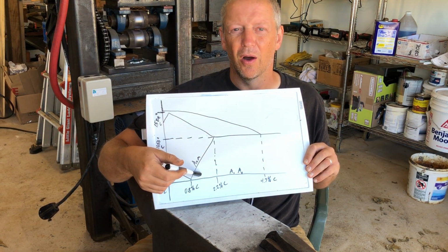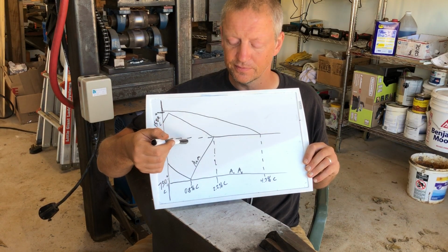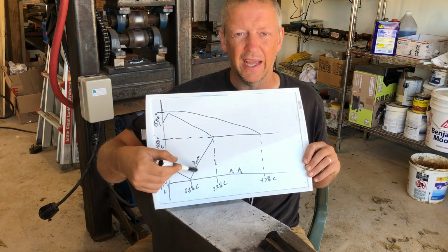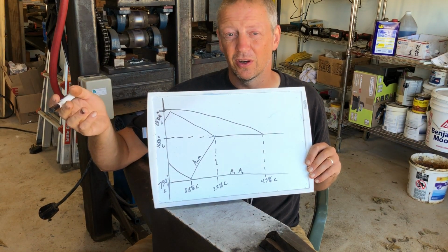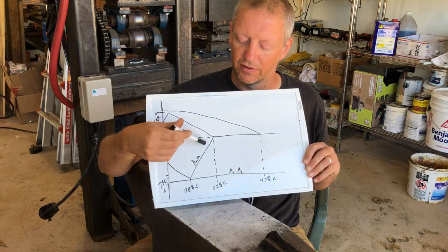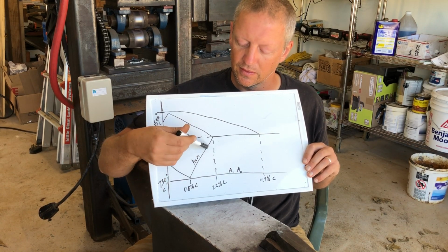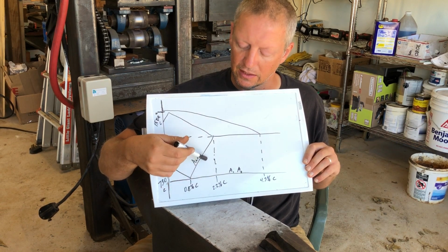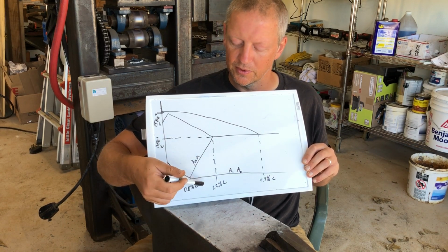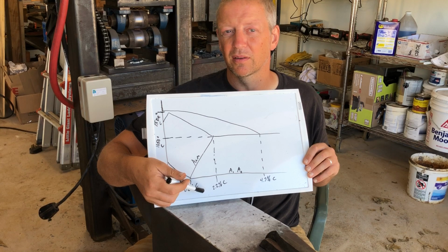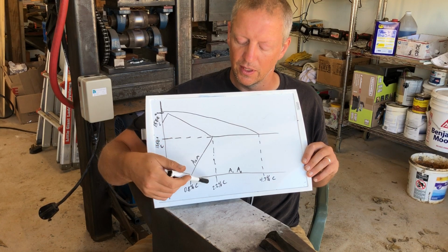Depending on how large your carbides are, depending on how fast you are heating, it's going to actually affect the location of this line. As I noted earlier, adding alloys affects the location of this line. So we're really going to be talking about the ACM line and this zone over here, which is really where we're talking about with Wootz, from about 1.3% carbon, maybe 1.2% carbon, up to about 1.8% carbon.